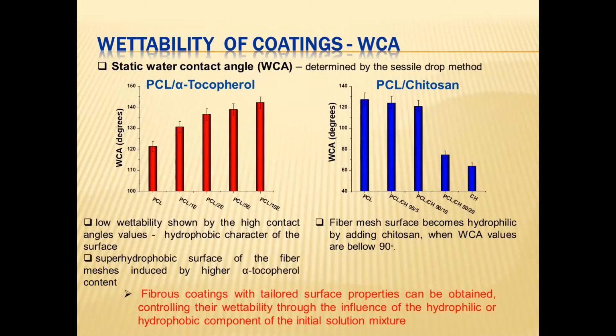The wettability of the coatings was investigated by static contact angle measurements, static water contact angle measurements determined by the sessile drop method. The values of the contact angle obtained showed a low wettability due to the higher values, showing the hydrophobic character of the surface, and even a superhydrophobic surface in the case of fibers with higher tocopherol content, the values of the water contact angle being above 130, even 140 degrees.